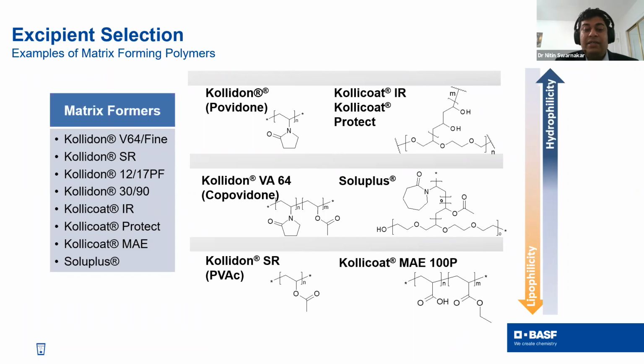So you make a matrix and you want to see diffusion of the drug up to like 24 hours, you can do that with Kollidon SR. Sometimes people want to mix and match the release profile. So you can blend Kollidon, which is on the top, with Kollidon SR, so that you can make a pore former and you can create whatever matrix you are looking for. It's going to be very, very useful for the formulator.